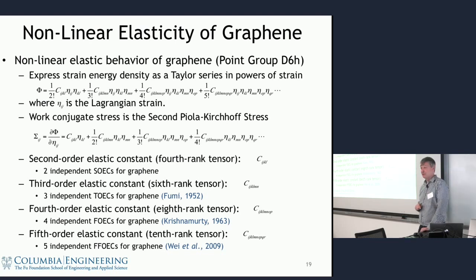But it turns out that the magic of group theory rides in to save the day to a great extent. I would say the vast majority of the terms in these 10th rank tensors, or 10, 8, 6, 4, are related. And it turns out that in this second order elastic constant, you only have 2 independent terms. Again, that's the Young's modulus and the Poisson ratio. The third order term only has 3, then 4, and then 5. So altogether, going out to this fourth order term, or fifth order in energy, fourth order in displacement, you only have 14 elastic constants. Not so bad, better than 1,300. Still, how the heck do you get that from experiment? The answer is you don't.